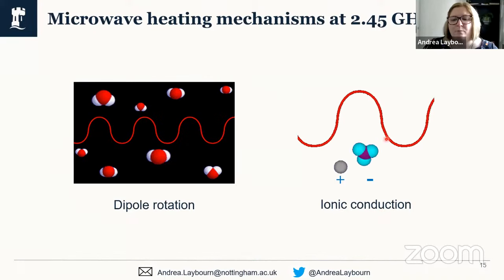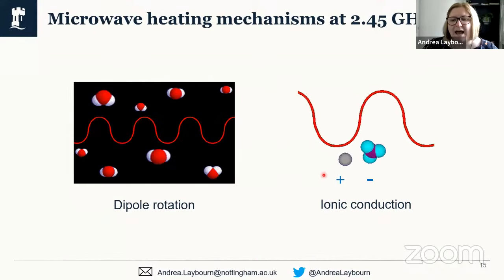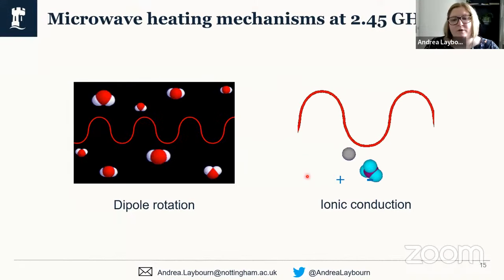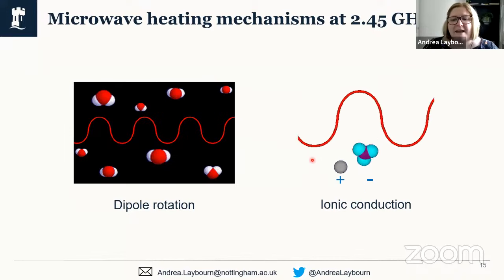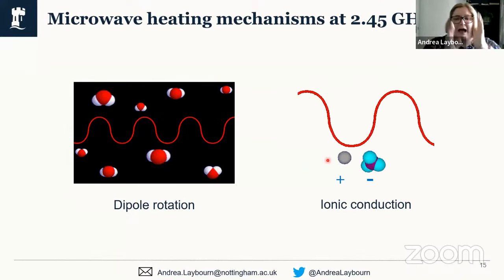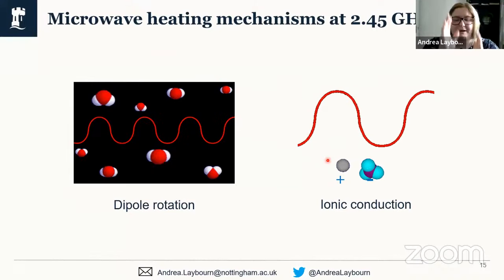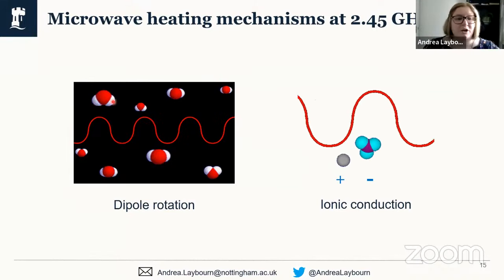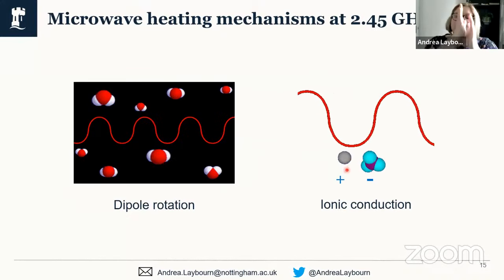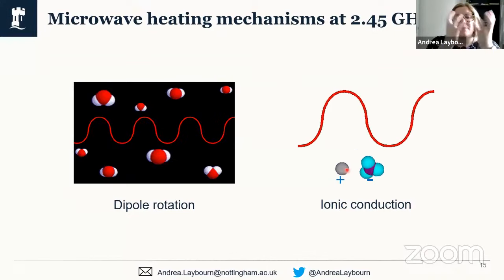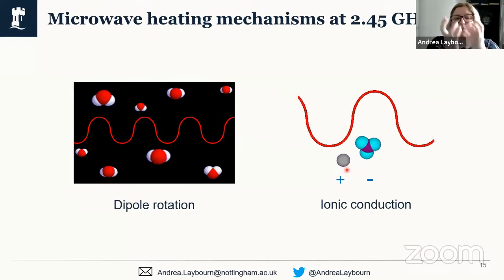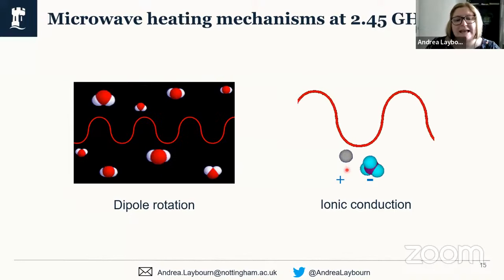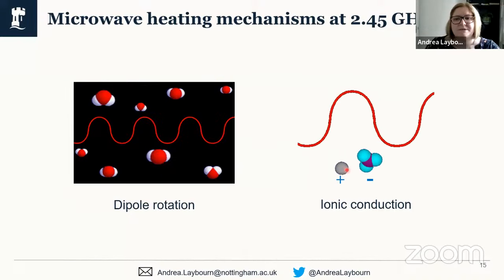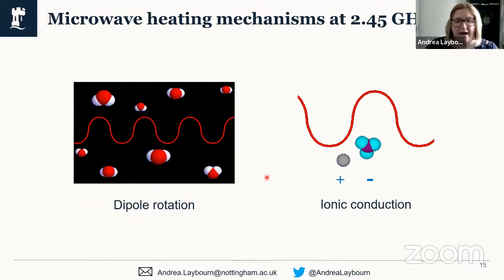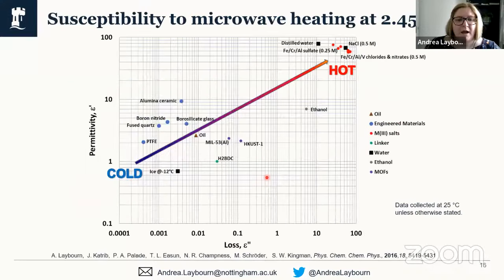On the right-hand side, we've got ionic conduction, which is if you have ions present within your reaction mixture or within the material that you're treating, then the ions also move relative to the high and low electric field potential. In both cases, because you've got the dipolar rotation or the movement from the ionic conduction mechanism, these molecules are vibrating against each other and rubbing against each other and creating friction, which leads to the heating. And so these are the underlying mechanisms that would happen at this particular frequency of the electromagnetic spectrum.